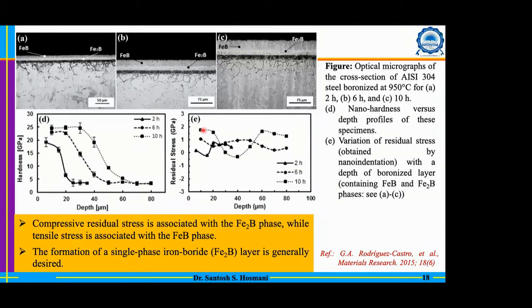There is a difference in their crystal structure. And ultimately that will determine the ability to withstand the stresses generated simultaneously in the FeB and Fe2B layers, because the properties of the FeB and Fe2B layers depend on the elastic strain. That means the capability of that particular boride layer to accommodate the elastic strain, which is generated due to the residual stress mismatch.